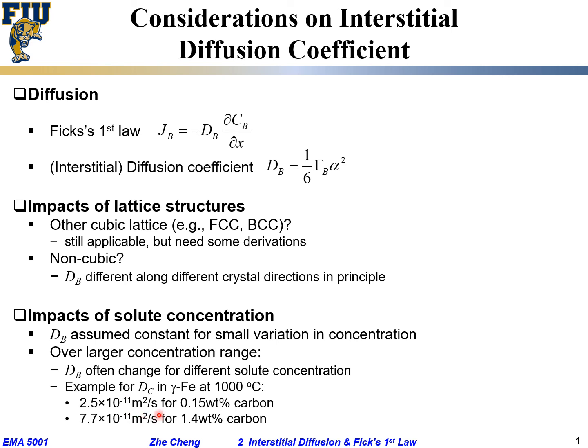You see, within a small concentration range we can assume the diffusion coefficient to be more or less the same, but over a larger concentration range, actually not very large, you cannot even assume that. It may change by three times.